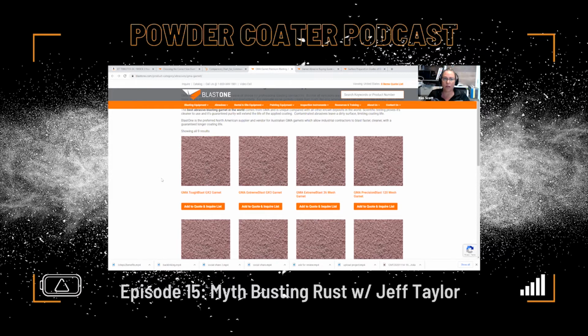Right, which was popular. It said on there that it was good for powder coating. Yep, it is. It is excellent for powder coating. If you want to go one step up from there, you go into your GX2. Your GX2 is a blend of 36 and 80. And the reason you want to go with GX2 is if you had a really heavy coating up to about 25 mils thick, and you wanted a higher profile. So if you're ever working on a job where you've got a really tough coating that you want to get off, up to, let's just say, 25 mils thick, this is an excellent abrasive. It's going to help cut that quickly. It's going to get you between a 2.5 and 3.5 anchor profile.